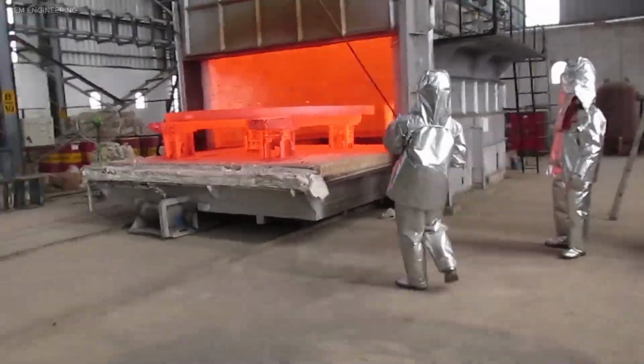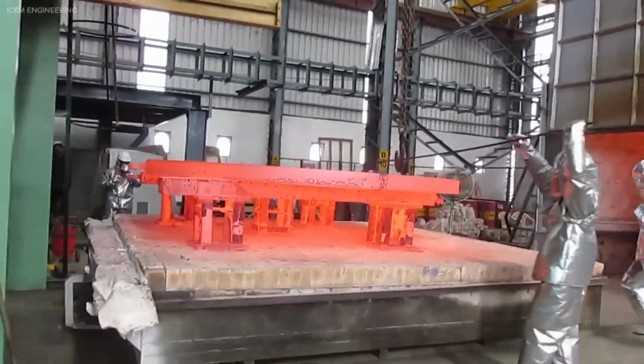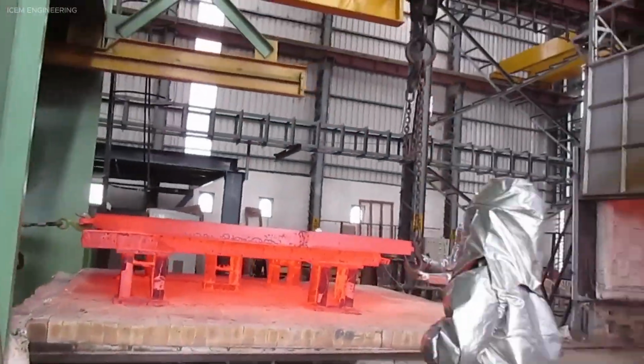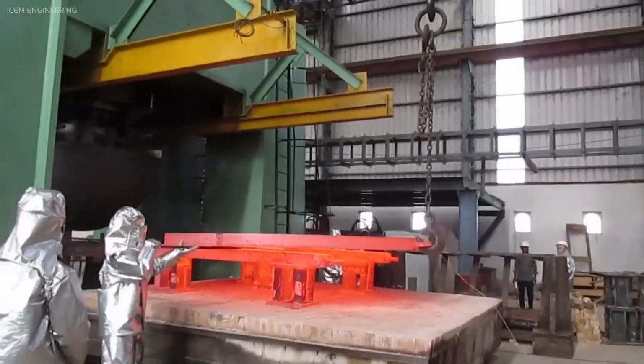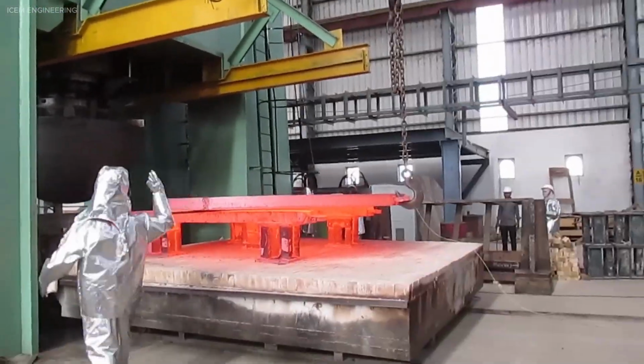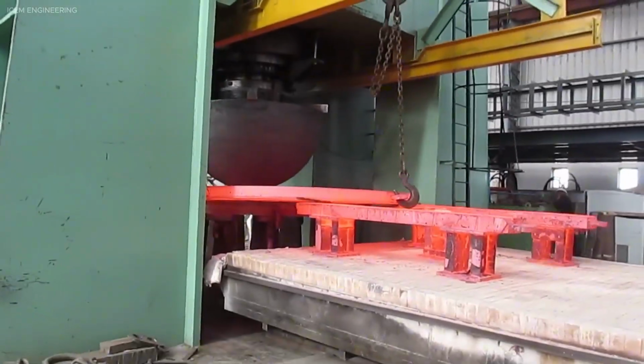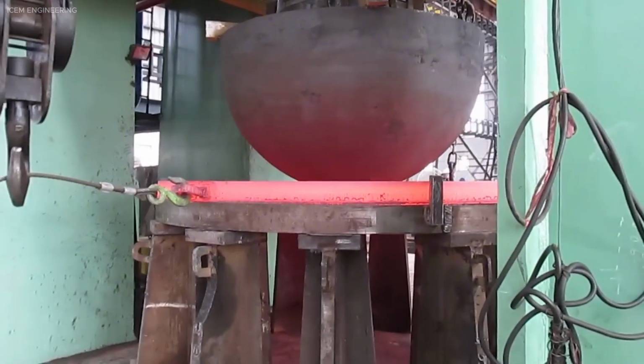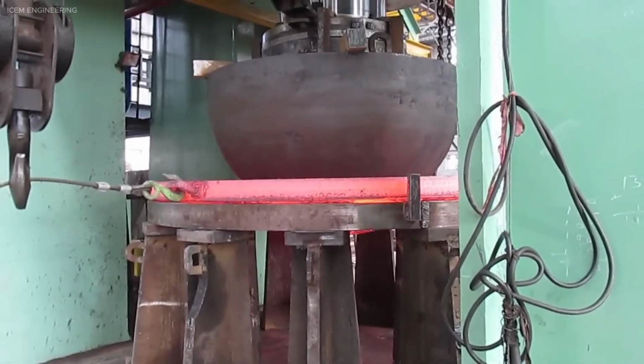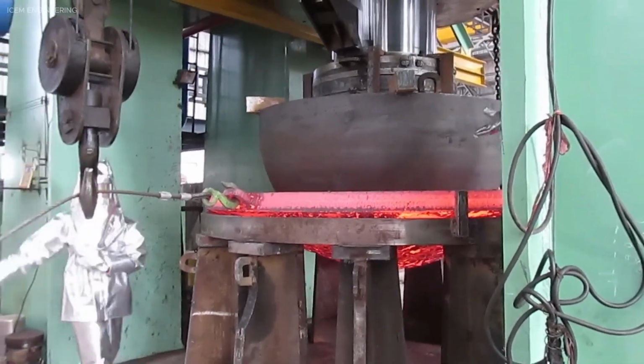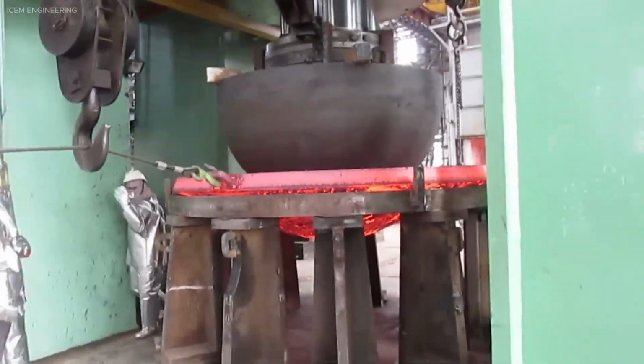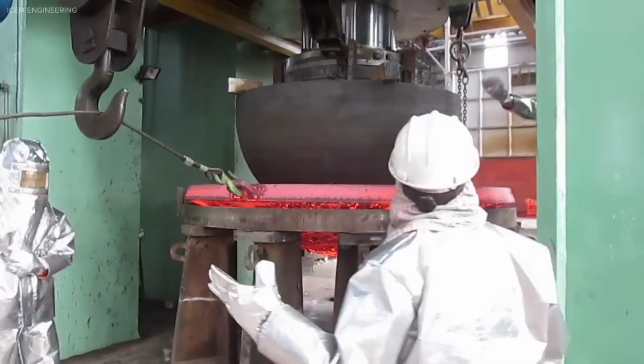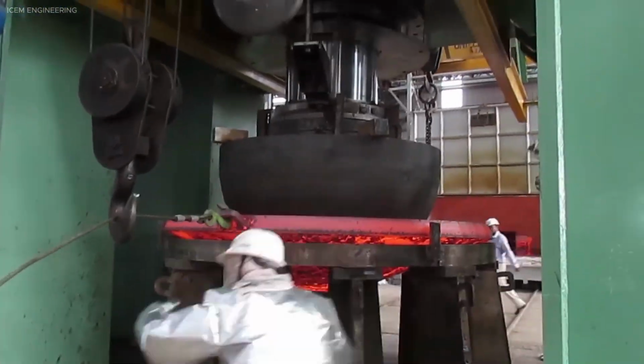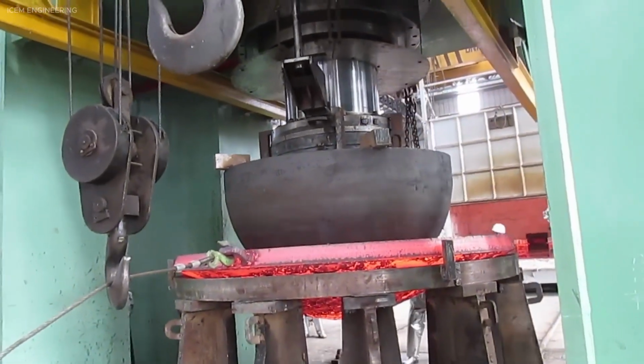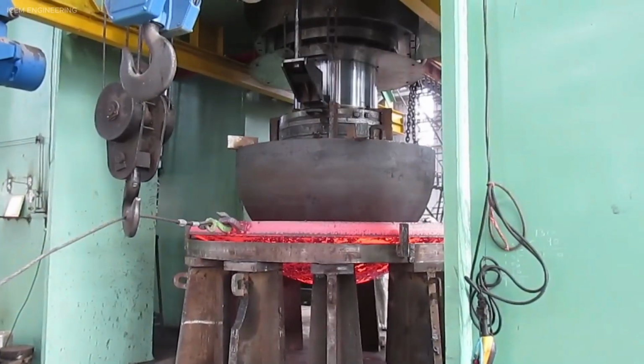At ICEM Engineering, hot forming of a 125 mm thick Hemi head begins with heating a steel plate to forging temperature, typically around 1200 degrees Celsius. The heated plate is then placed into a pre-shaped die. Through controlled hydraulic press forming, the material is gradually shaped into a hemispherical head under high pressure. Continuous temperature monitoring ensures the material remains ductile during deformation.